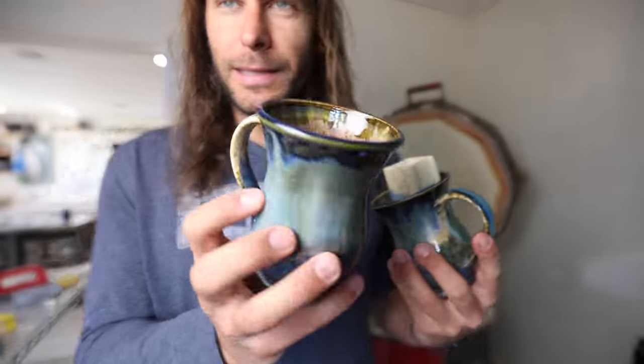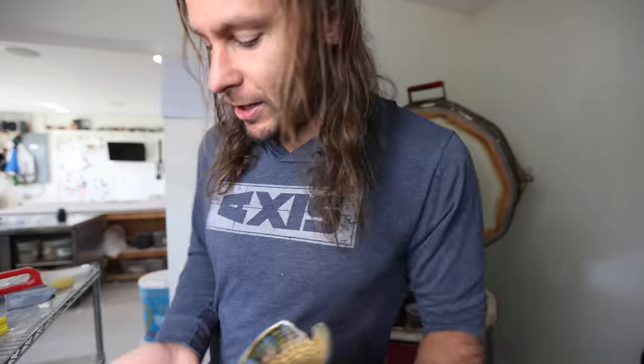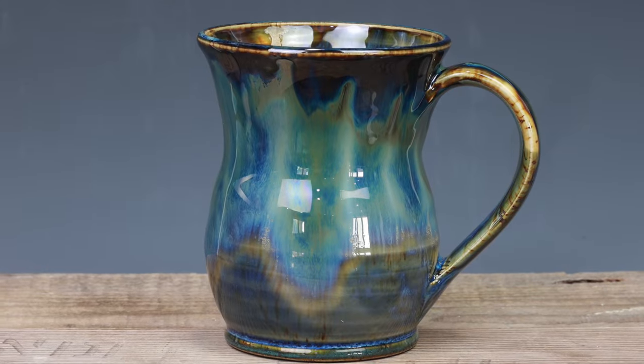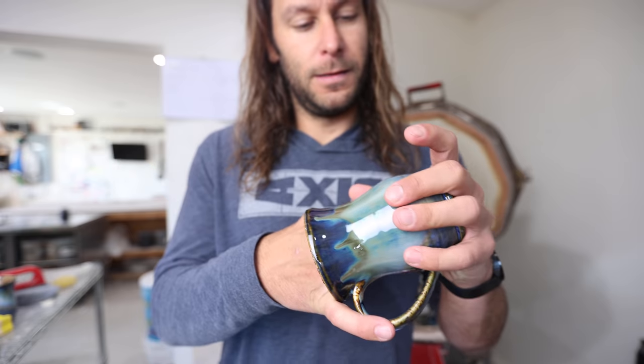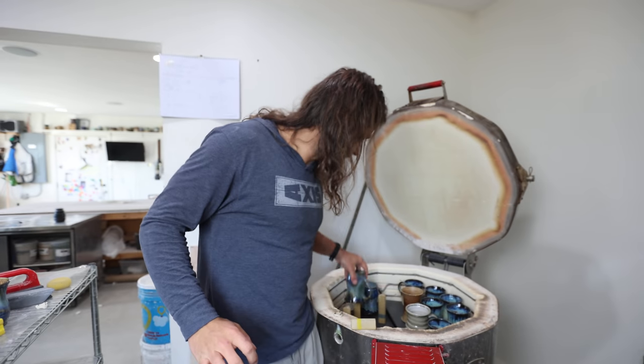Two of them stuck — the kiln post stuck to the side. So those didn't work. I had such a good track record going before. This one worked out, so I'll probably only have like five in this restock. And this one is like the worst insanity mug result — it was resting on the kiln shelf. Usually I get most of them to work out, but this one didn't work out so well. This one didn't quite get as many crystals — you can see the crystals in there. Sometimes there's a bunch, which means this kiln must not have cooled very slowly.